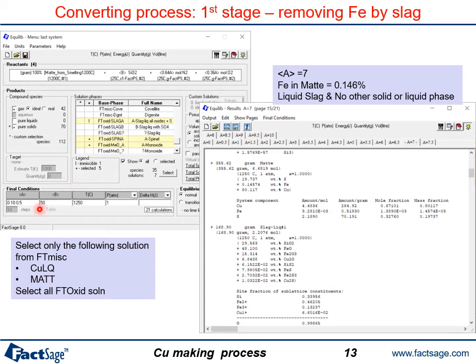And we set the B in this case as 50 gram, and then A we are changing from 0 to 10 in 0.5 mole steps. Okay, and then the temperature is set at 1250 degrees Celsius. Even in this case, of course, the database selection is the same as our smelting process. Okay, so once you do all the calculation, you can check all the results, and the best one I found was A equal to about 7.